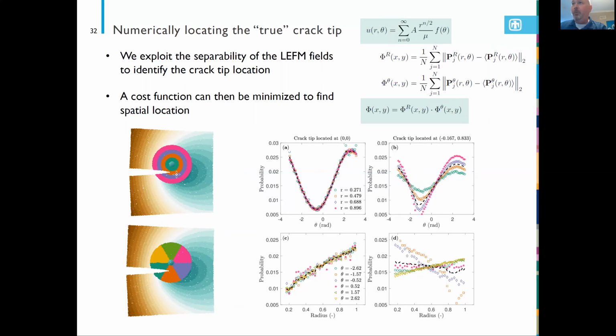The presentation was getting long, and I really just didn't want to incorporate too many specifics that I didn't think were so dramatic. But you're absolutely right. That's one of the challenges here: we're applying linear elastic fracture mechanics, which assumes a sharp crack. We don't have a sharp crack. We might be in a plastic regime. However, it seems as though we're in a regime that is radially K1 dominated, and that's a good indication that linear elastic fracture mechanics approaches might be applicable at this length scale.